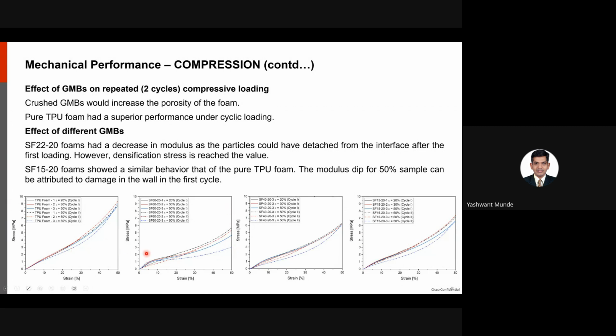So in a nutshell, when we strain the foam to 20% strain and then reload it up to 50%, we see that the pure TPU and the ones with smaller GMBs have practically no difference, whereas the ones with the bigger ones do show a difference. This difference increases tremendously when the first cycle is to 30% strain and when the first cycle is at 50% strain, indicating severe particle crushing in these and very little or none in these two. So this also indicates that we have very good densification when we have smaller GMB particles reinforced in these TPU foams.